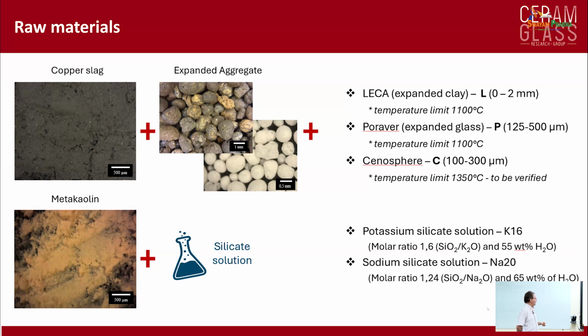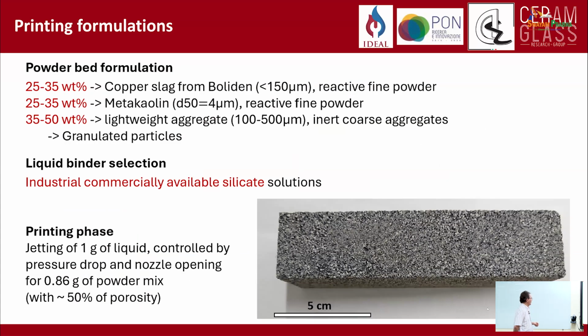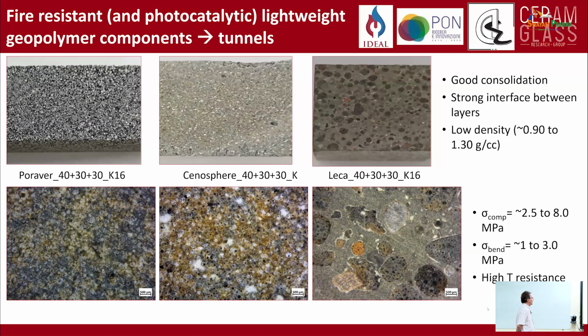And we used both potassium silicate and sodium silicate solutions. So we used a combination of copper slag, metakaolin, and lightweight aggregate. And we used only industrial commercially available silicate solutions. And you can see that we are able to obtain consolidated parts. You can see here the morphology of different parts containing the various lightweight aggregates. And you can certainly recognize the porous aggregates coming from expanded clay. They are very well embedded inside the geopolymer matrix.